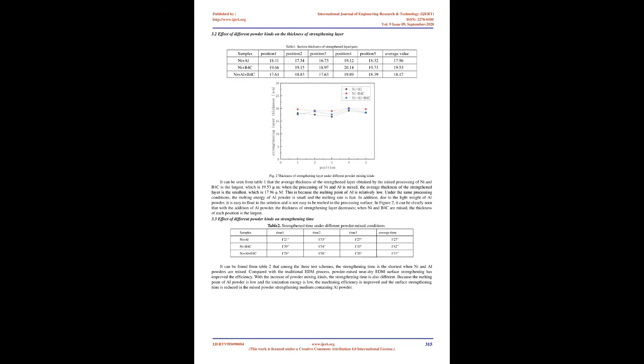1, it can be found that the structure of strengthening phase is formed on the strengthening layer, and the surface of the strengthening layer is uneven. However, under the condition of different kinds of powder mixing, the surface morphology of the strengthening layer is slightly different, and the shape of the strengthening phase is different. This is due to the different characteristics of Al powder and B4C powder added in the process of EDM strengthening.